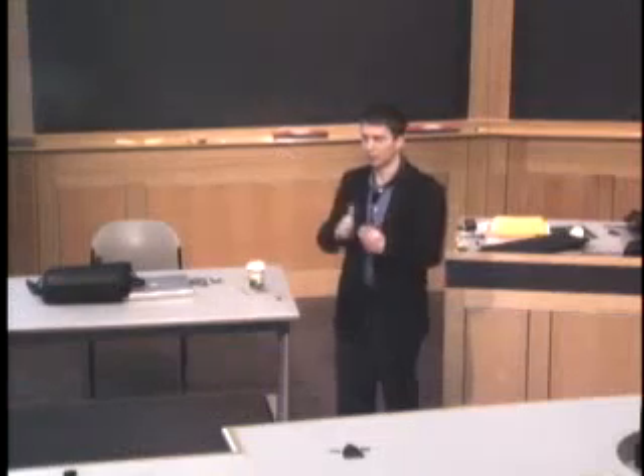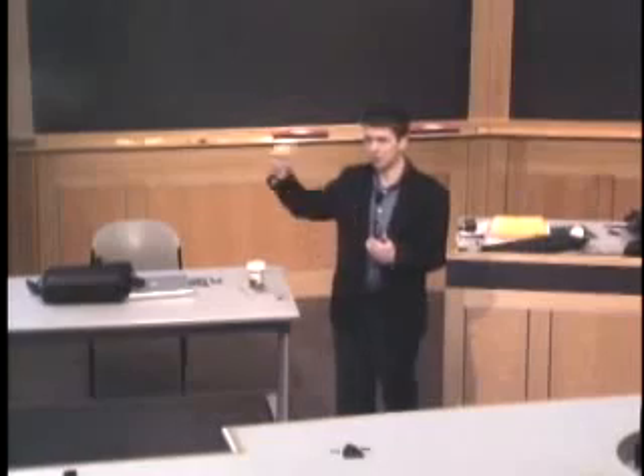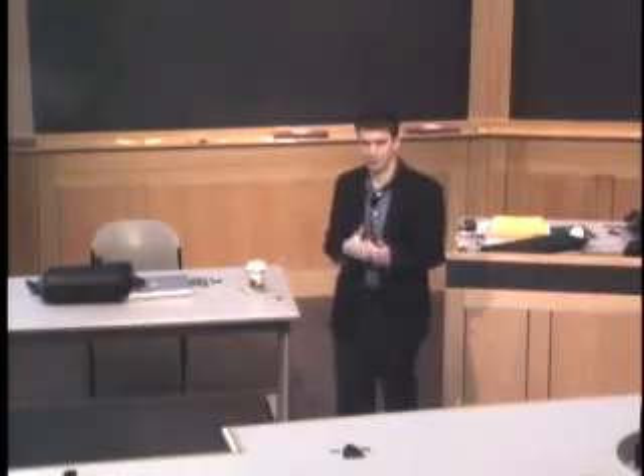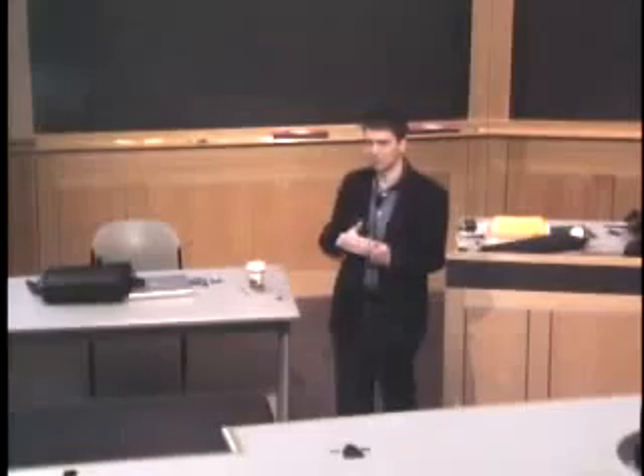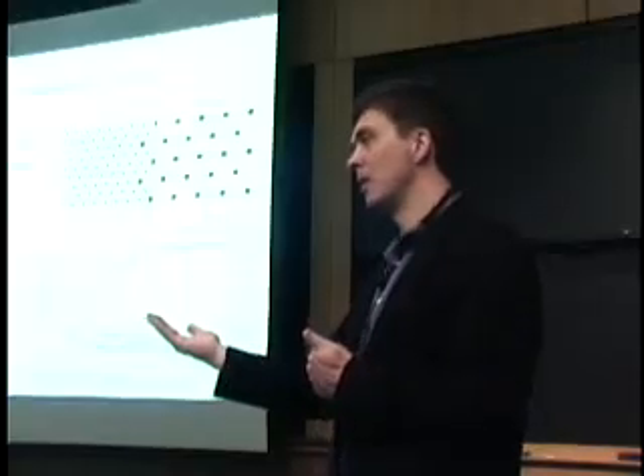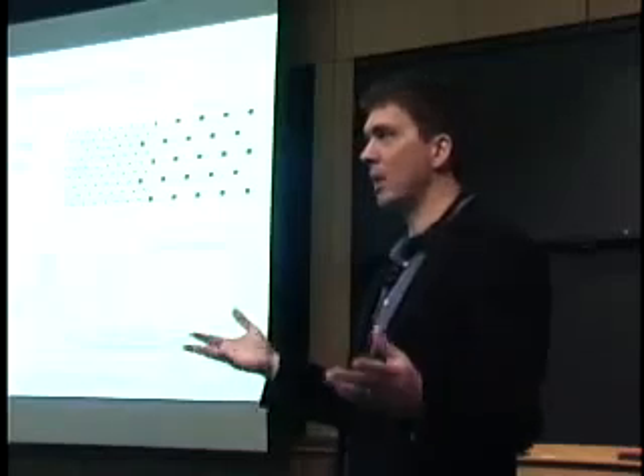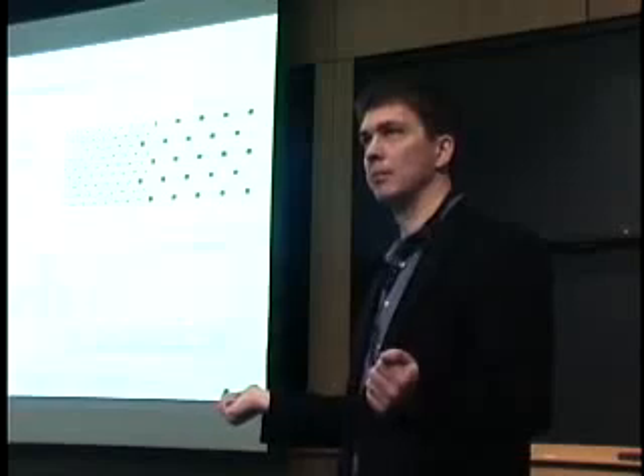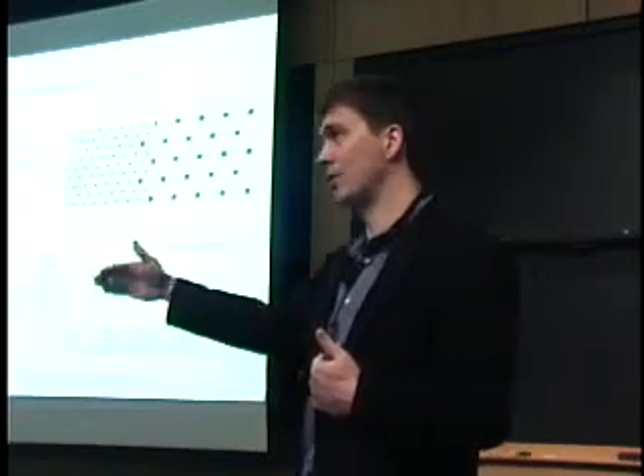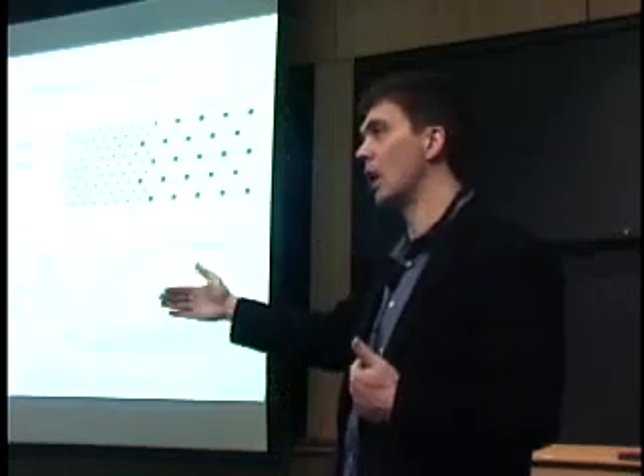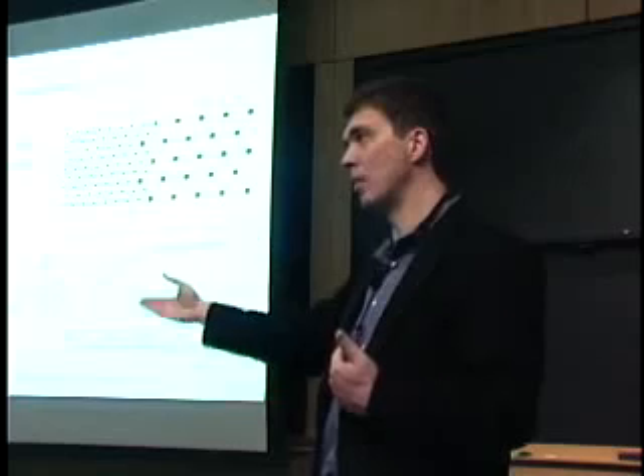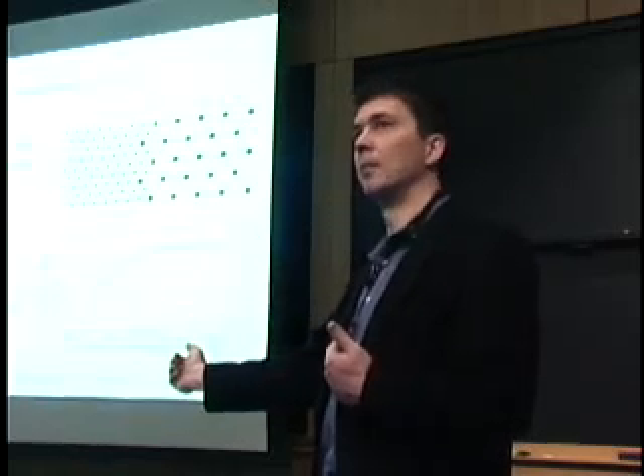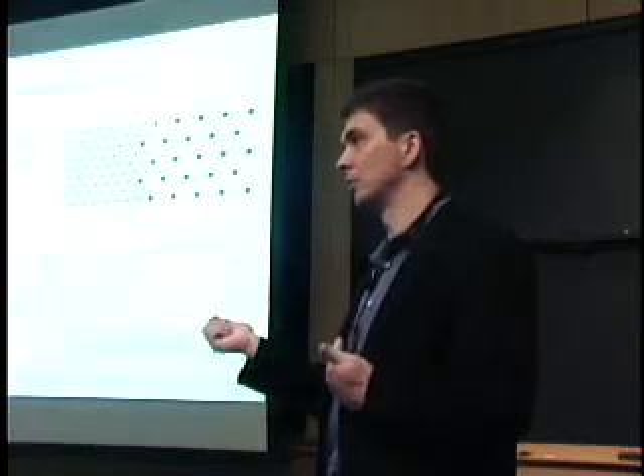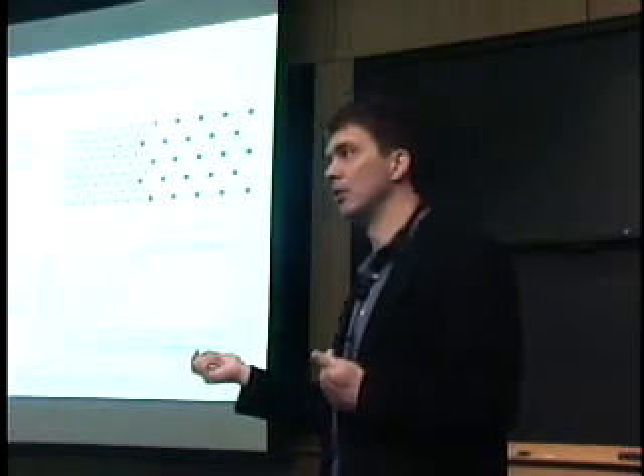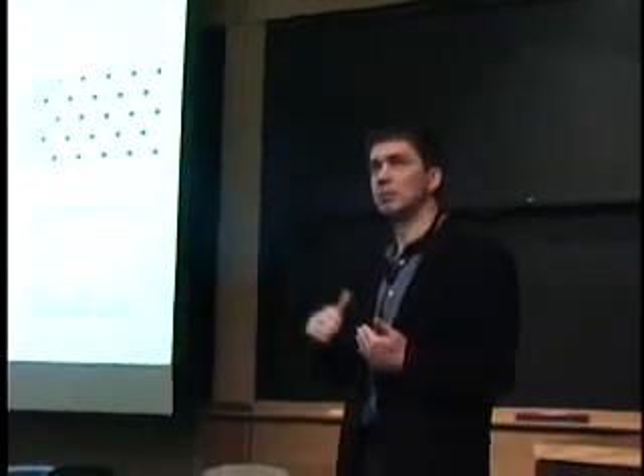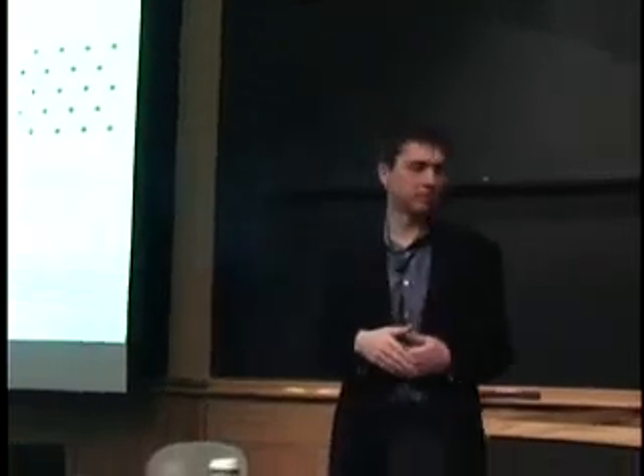That means phonons are usually the first thing to see something far away. They're the first thing to see finite size effects, and the first to see scattering off interfaces. The reason is that a lot of systems behave fairly harmonic at low temperature, so phonons just travel and travel, and their probability of being scattered is low, since it's only as they become anharmonic that they scatter. Of course, they could scatter off disorder, so in disordered systems the mean free path is a lot lower. But often phonons see hundreds of angstroms far, essentially.